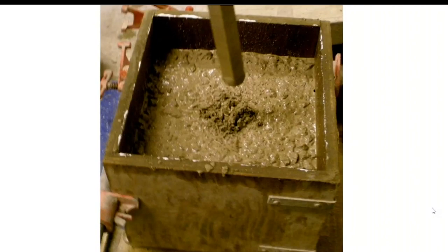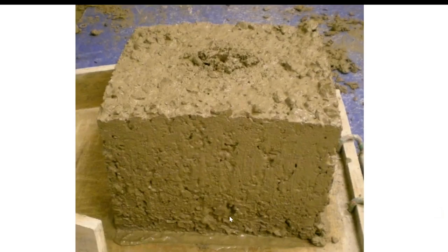It's consolidated the concrete. You immediately take the edges of the box off and you look on the outside. Whoa. What are you looking for? If there were lots of voids here, that would be bad. That means the energy wasn't enough to reach the outside. Also, you look at the edges, and you look, are they crisp? Are the sides straight up and down? And these are the measurements you take in the box test.